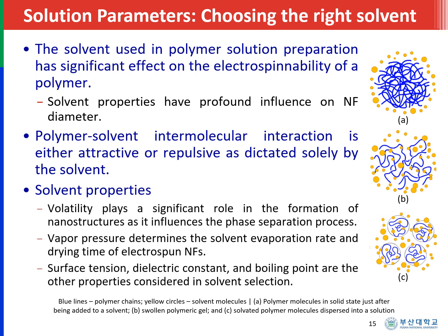Volatility plays a significant role in the formation of nanostructures because it influences the liquid-solid transition or the phase separation process during electrospinning. Vapor pressure, on the other hand, would determine the solvent evaporation rate and drying time of electrospun nanofibers. Surface tension, dielectric constant, and boiling point are the other properties that you should consider in solvent selection. They may not be as important as volatility and vapor pressure, but you still have to consider them.